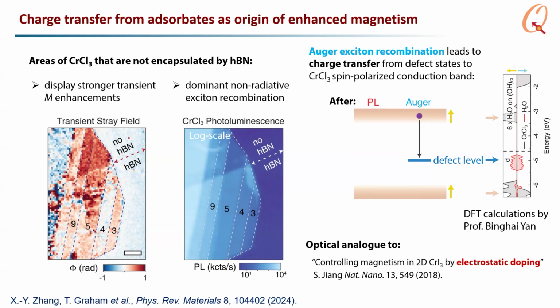We work with the DFT group led by Professor Binghai Yan, and they said that indeed hydrogen bonded H2O on the surface of this material could provide the right unpolarized defect states within the band gap. When non-radiative exciton recombination happens, these unpolarized defect electrons become polarized. So maybe not very interesting, but the technique is very interesting for measuring optically induced magnetic fields, including, say, an optically induced Meissner effect or otherwise.